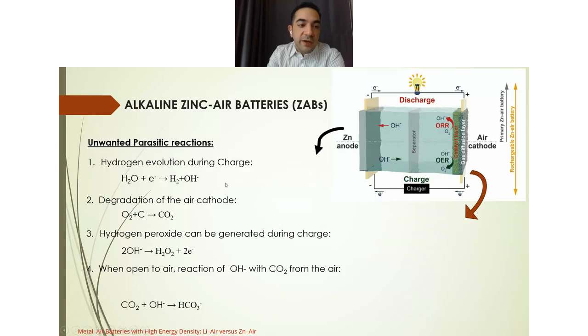The second is the degradation of the air cathode, especially during charging. As I stated earlier, we generate oxygen bubbles, and this oxygen gas can sometimes react with the cathode material in the air electrode and form carbon dioxide, which, especially during cycling, will end up destroying the air cathode and degrading it, and make the shelf life of the battery limited. The third is that you may end up producing hydrogen peroxide rather than water. Through a two-electron pathway reaction, the hydroxide ion may turn to hydrogen peroxide, rather than the four-electron pathway reaction that will end up generating water molecules.